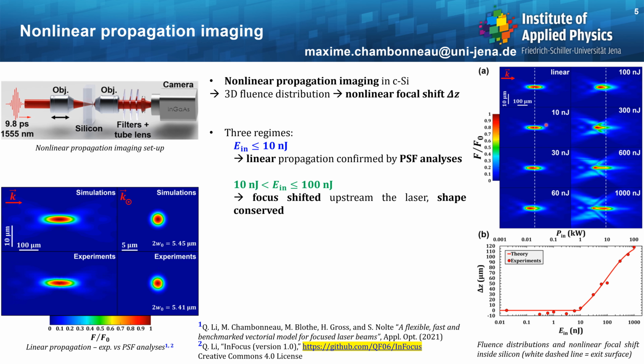Then for intermediate input pulse energies up to 100 nanojoules, you can see that the focus is unambiguously shifted upstream the laser. However, the overall shape is conserved. And then for very high input pulse energies, you can see those focusing and defocusing dynamics, meaning that we entered the filamentation regime. So to conclude on this, increasing the input pulse energy leads to an energy deposition which will be far from the interface.